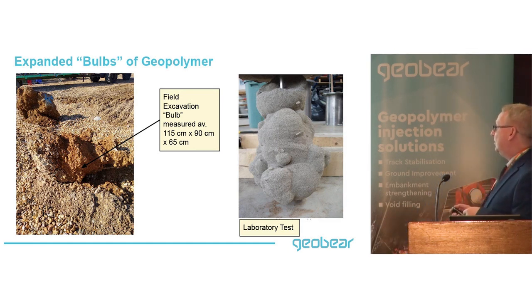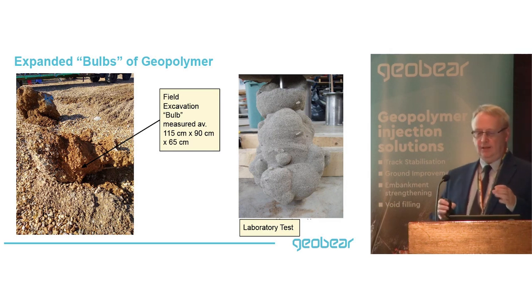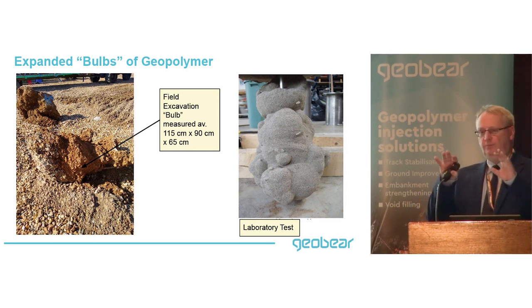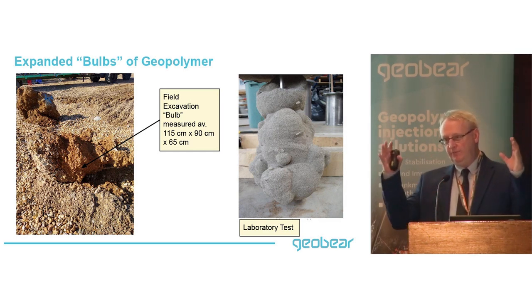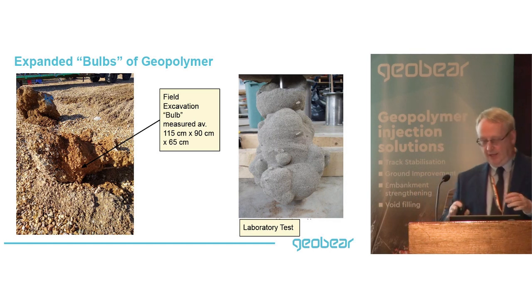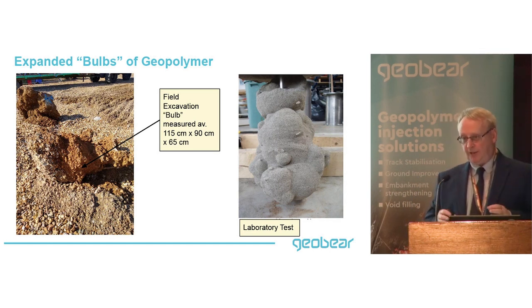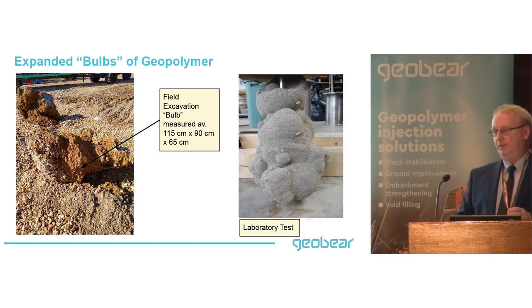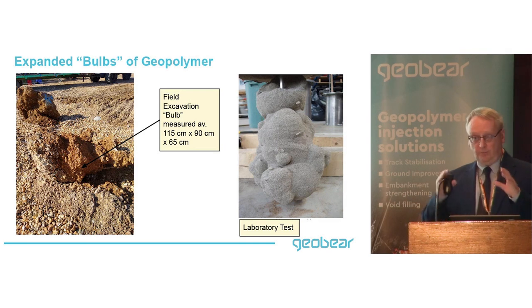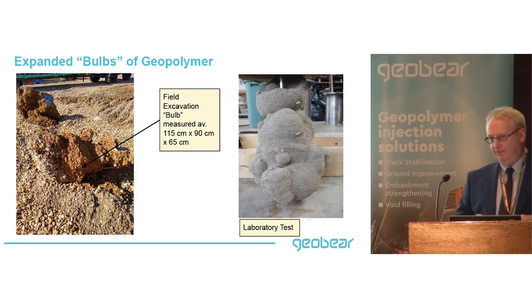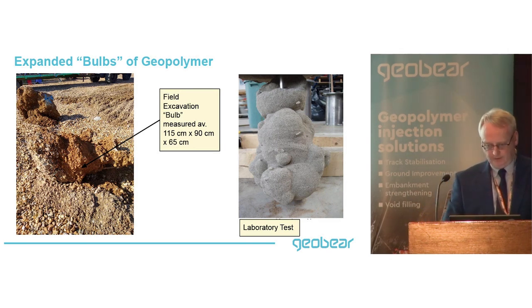Here's a smaller lab bulb done in one of these test cylinders using sand, a finer grain material, but essentially the same thing is happening. The polymer permeates through the pore space and then expands to form this bulb, and it's that expansion that causes compaction. So in granular soil, we increase bearing capacity through compaction, not by creating fractures - quite different.